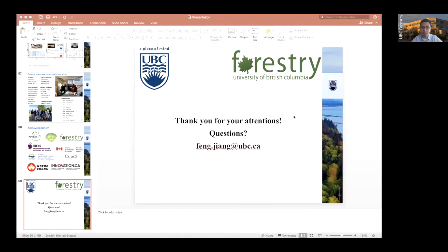Therefore, by converting those primary hydroxyl groups into carboxylic groups, which have a negative charge, those negative charges will repel each other and facilitate the breaking into nanofibers. I think there are a lot of reviews talking about TEMPO oxidation and sulfuric acid hydrolyzed cellulose, and hopefully you can check some online. So it's just my very brief answer.